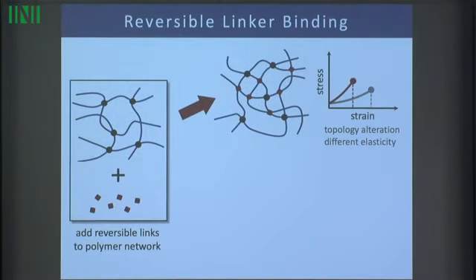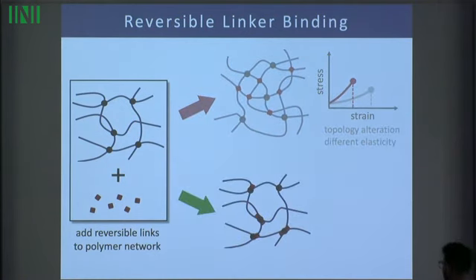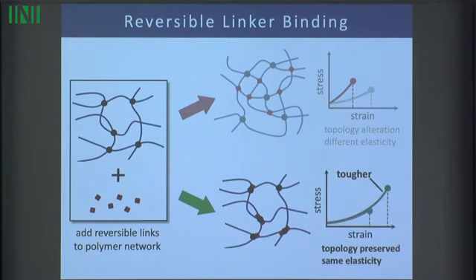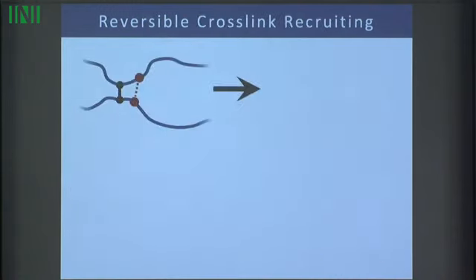Right? And so after some thought, you arrive at another possibility, which is that what if the reversible crosslinks somehow are biased to form bonds near the existing permanent crosslinks? Okay? If they do that, then what I'm doing is I'm mechanically reinforcing the permanent crosslinks at the local level, and I'm also not changing the connectivity of the network overall. It's the same overall topology. The question is, why would they do this from thermodynamics, and what are the repercussions of this?